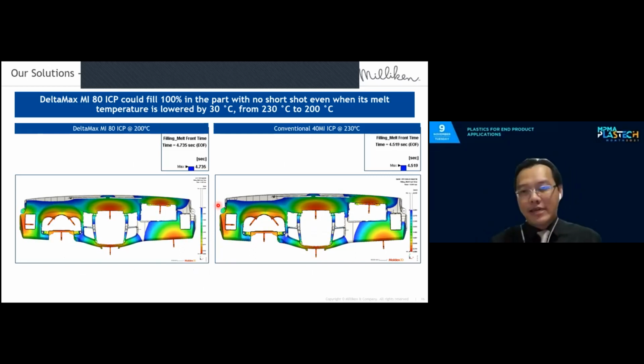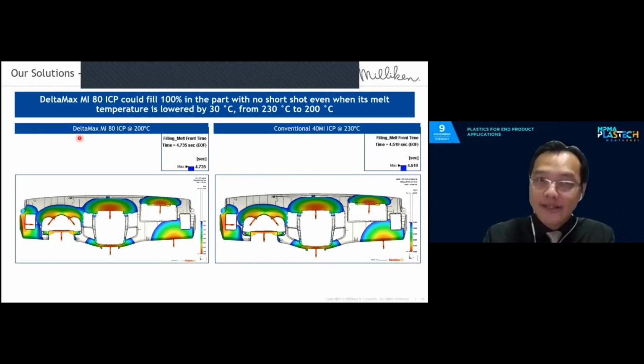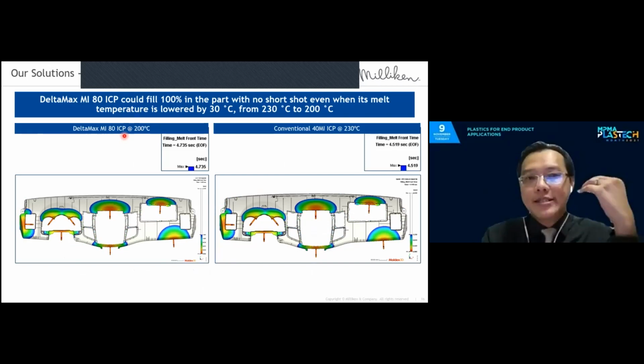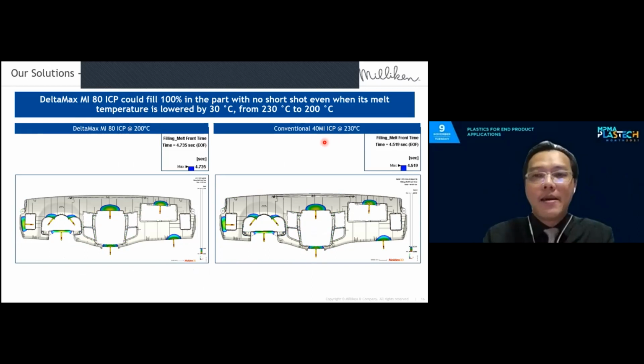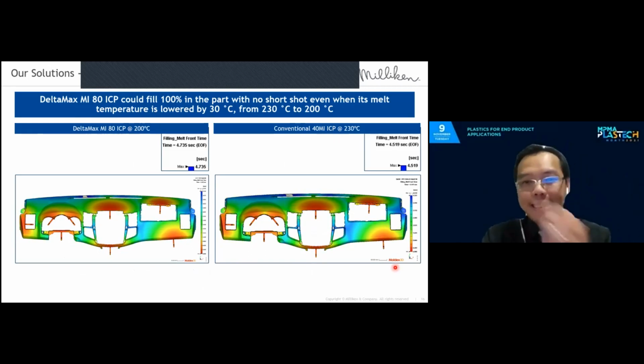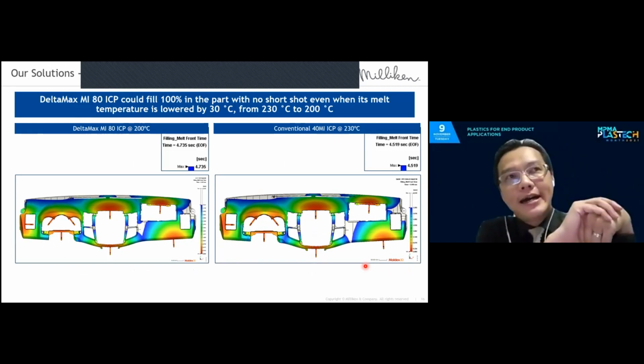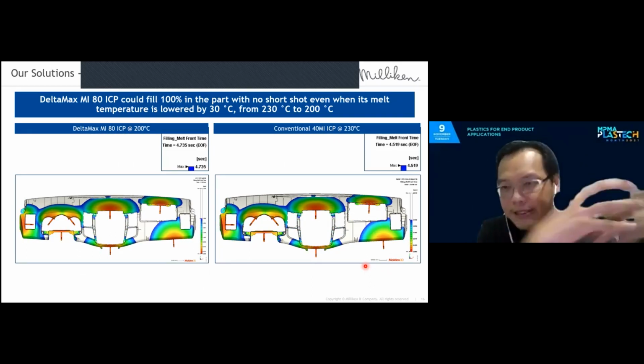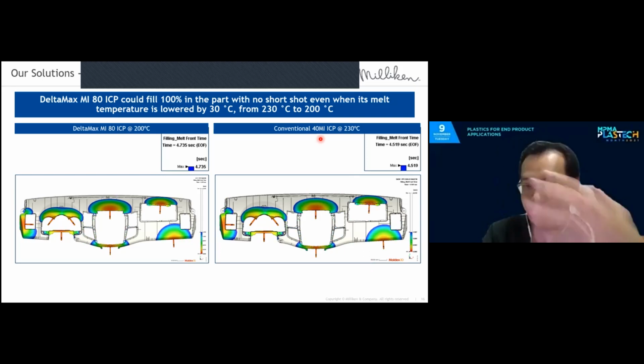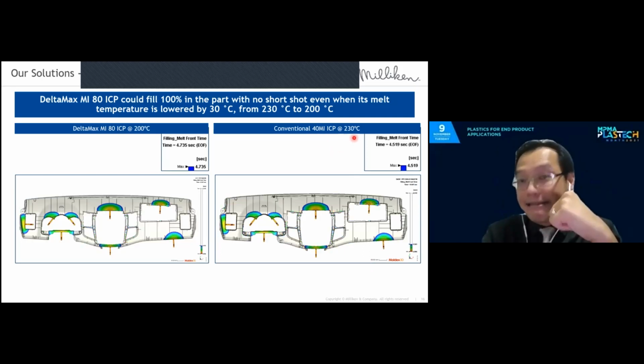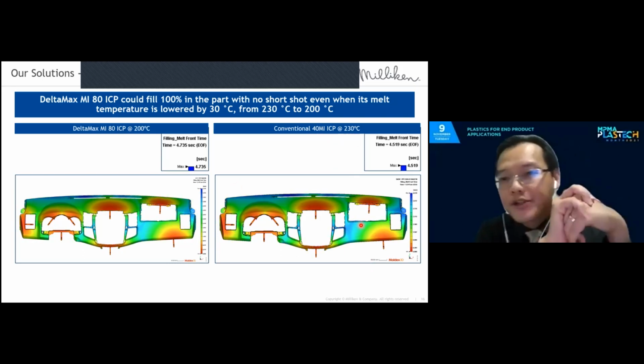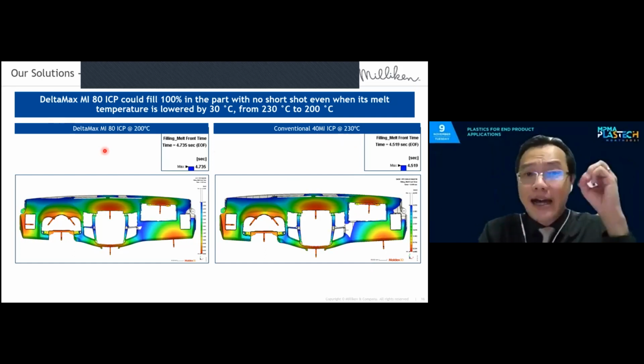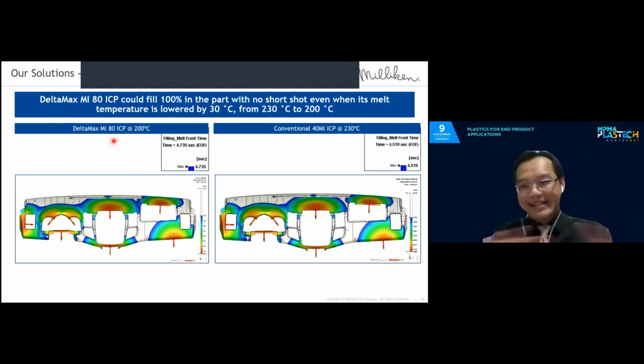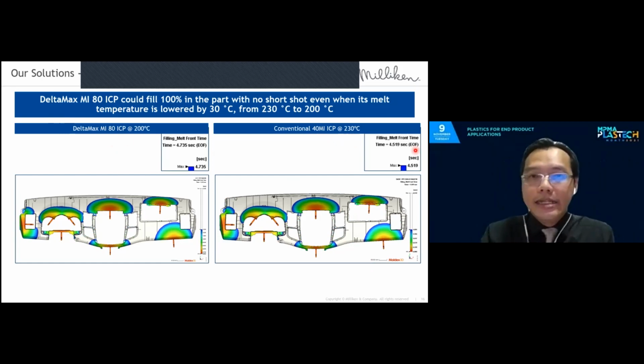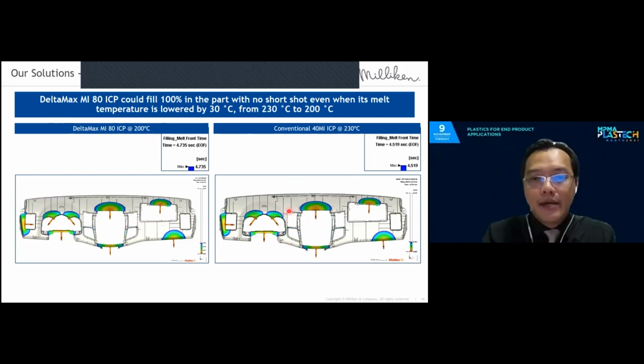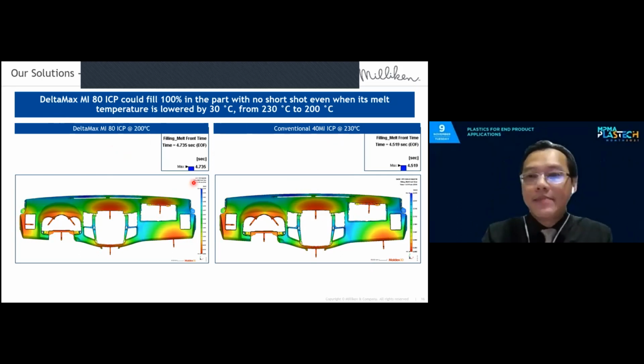And so this is a trial case, right? We worked with a customer and developed this Deltamax 80 MFR impact polymer, which has similar impact performance to a conventional 40 MFR ICP. We worked with Moldex3D and did some simulation. Of course, there are actual real mold trials, but this was a nice picture from simulation, where a 40 MFR control has to be injected at 230 degrees for this specific part that we chose, an automotive instrument panel. But because of the higher MFR, at again similar acceptable impact performance, we were able to reduce the injection temperature down to 200 degrees. And you can see there's no problem with filling, with similar filling times.